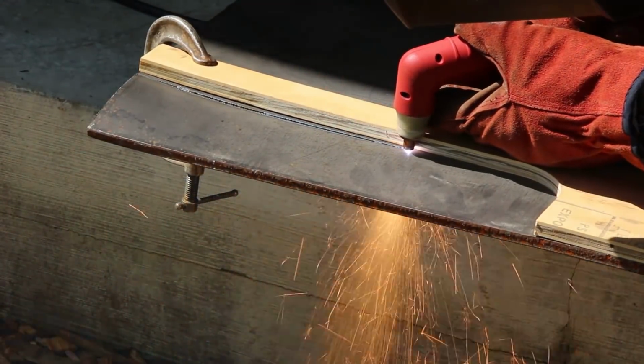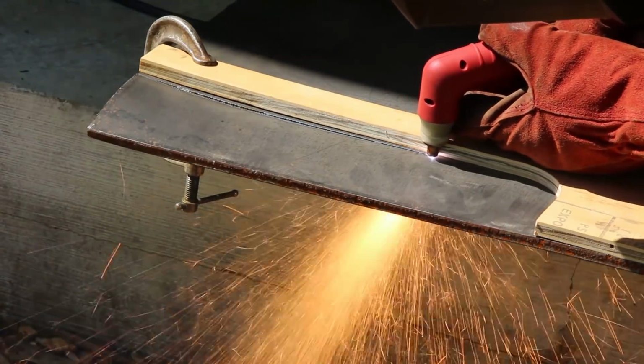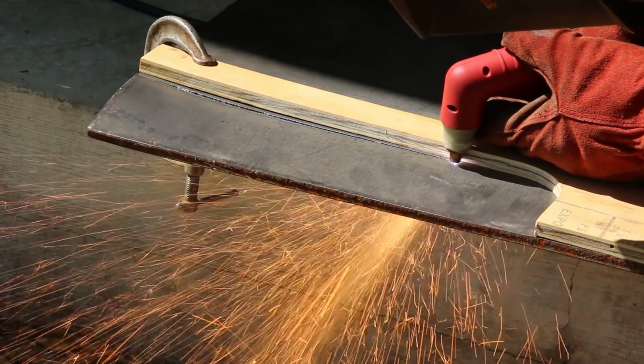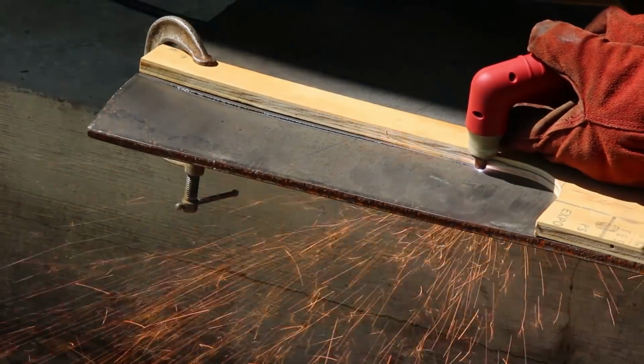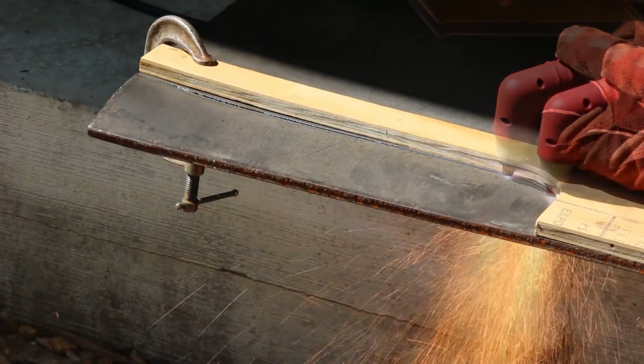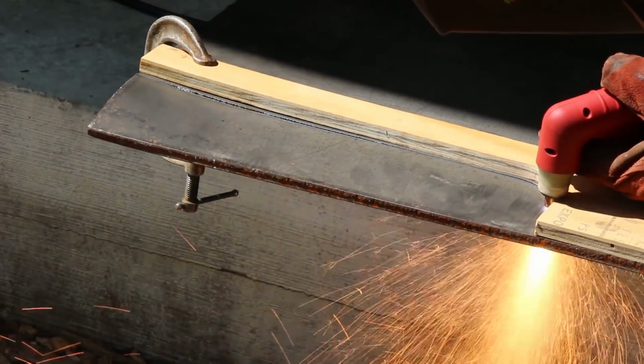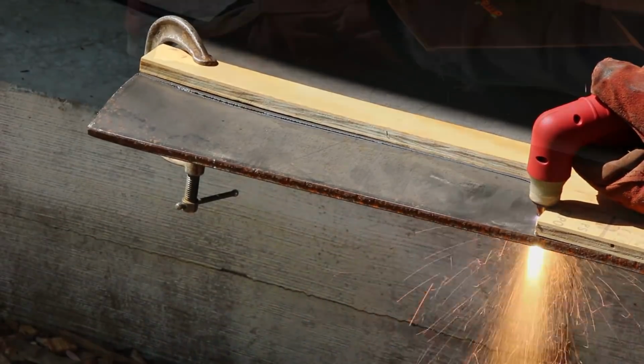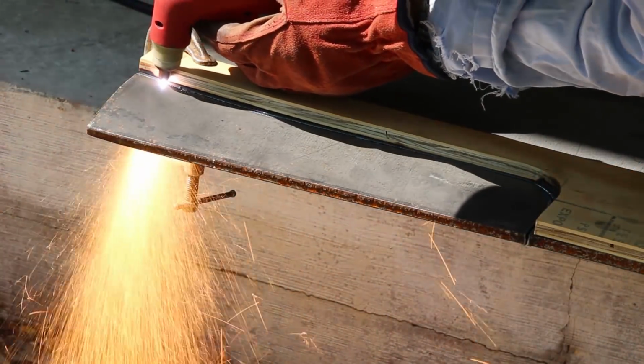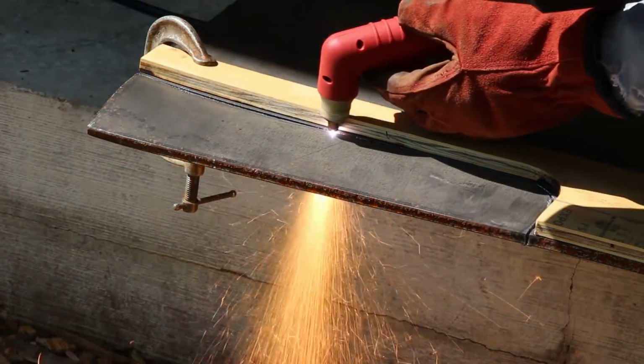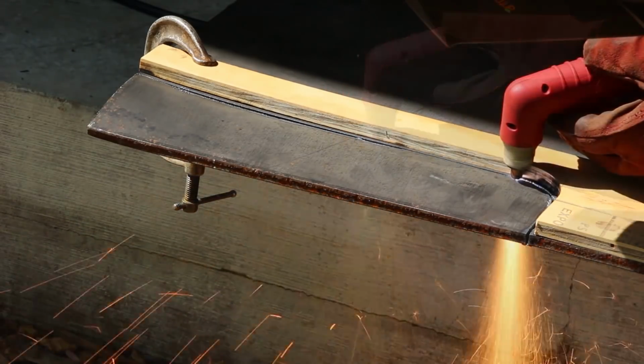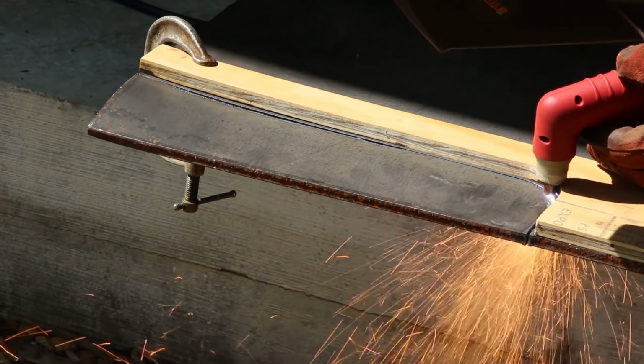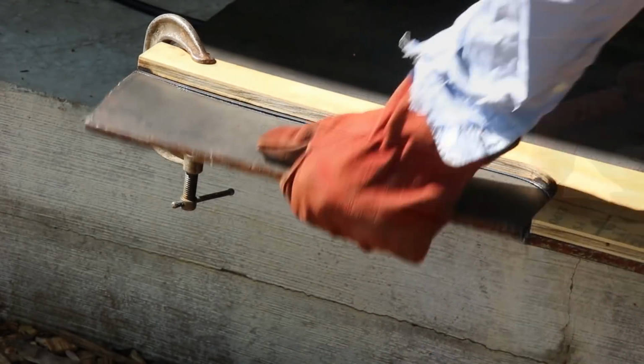As you can see, the plasma cutter is not cutting 100%, and that's partly because I'm not able to move it real smoothly along here. So every time it kicks up and you see the sparks shoot up to the top, it's not cutting 100% through. So since it didn't cut all the way through on the first pass, I'm going to have to do a second pass and run it down all the way, and it should cut all the way through on the second try.